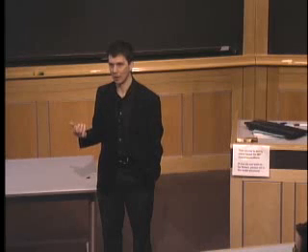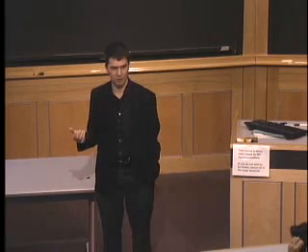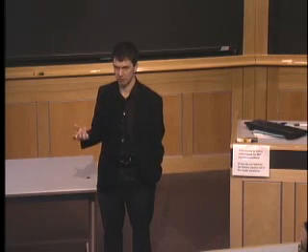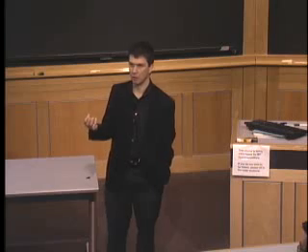There are a lot of people who say, well, if this doesn't work, I just need to change the parameters in my potential. There are certain things that you can never get right with pair potentials, because they are in violation of the particular form, which is a pairwise interaction. One is obviously that pair potentials count bonds. That's what you should keep in mind. The cohesive energy on an atom is largely determined by how many things are around it, because it literally sums bonds around it. It doesn't care much about the organization of atoms.